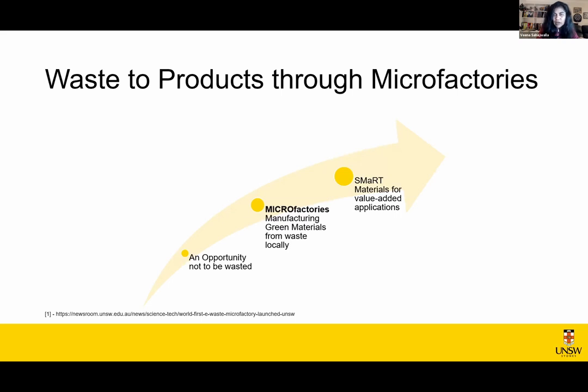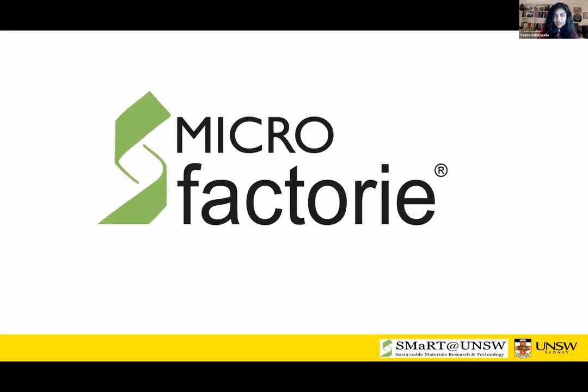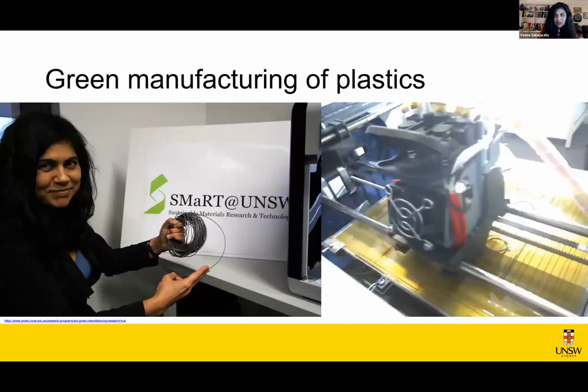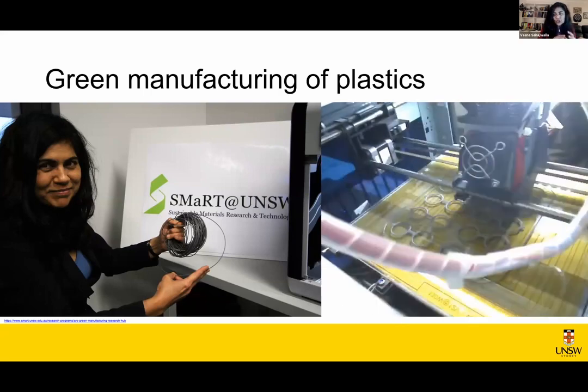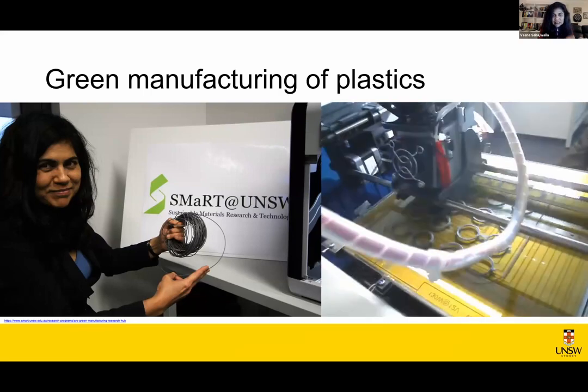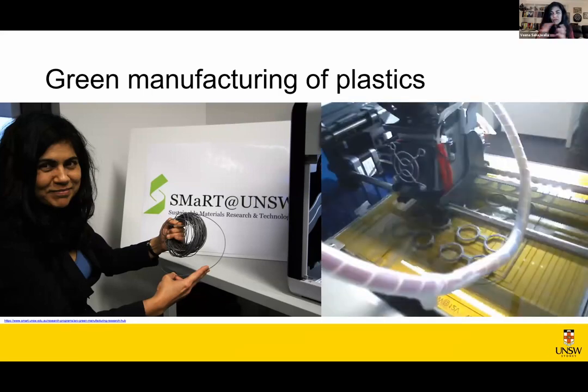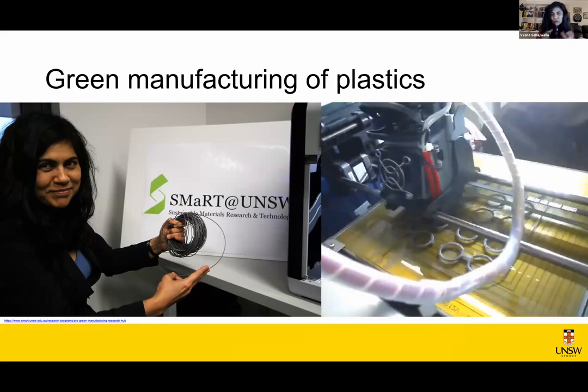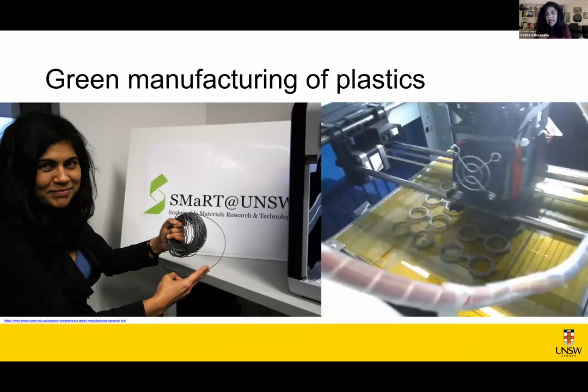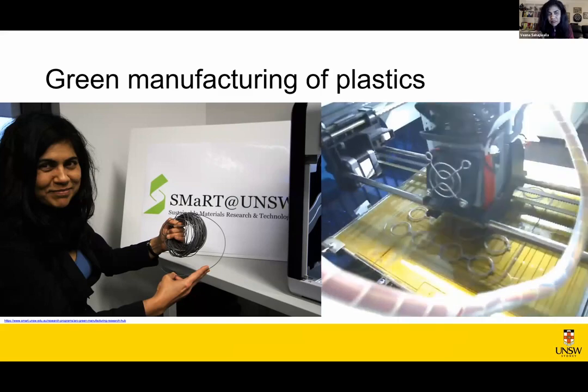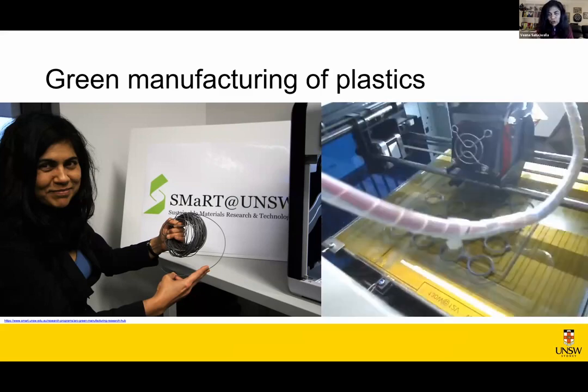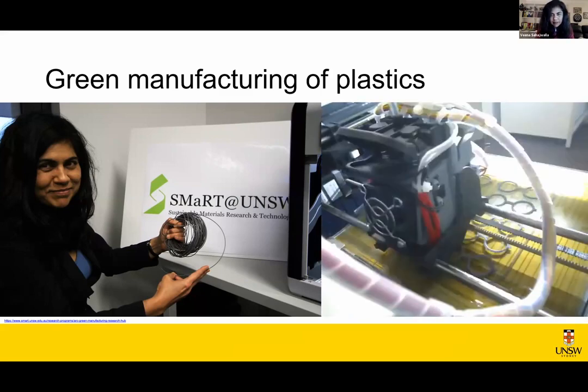And so if you had to do it in a local setting, we've also developed our micro factories on a small scale, many a times where you've got remote and regional communities, we can actually deploy these kinds of micro factories to show that plastics, as in this particular case, you're seeing converted into plastic filaments through our microfactory technologies, allowing us to then use those 100% recycled plastic filaments for 3D printing, as you're seeing happening there in that video.